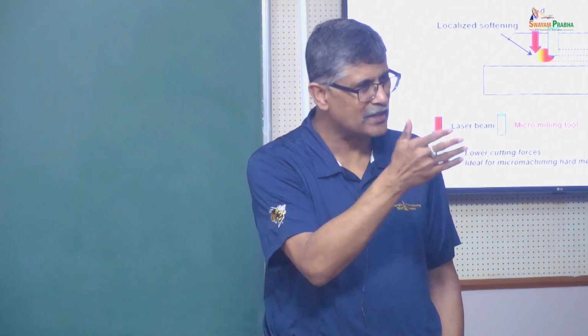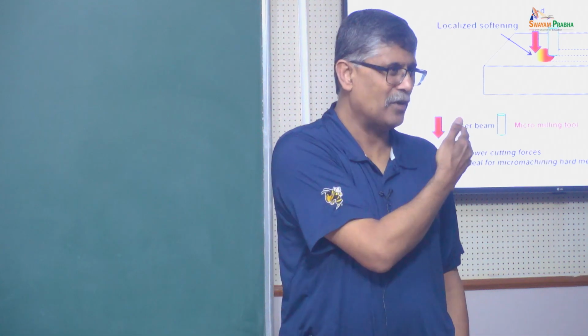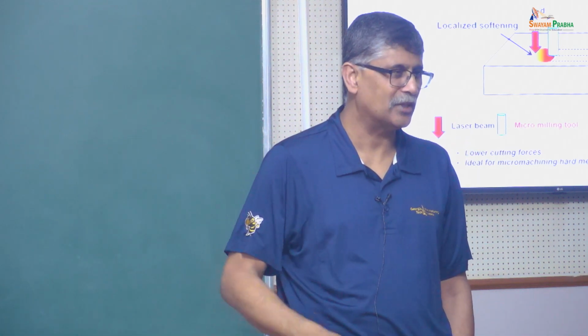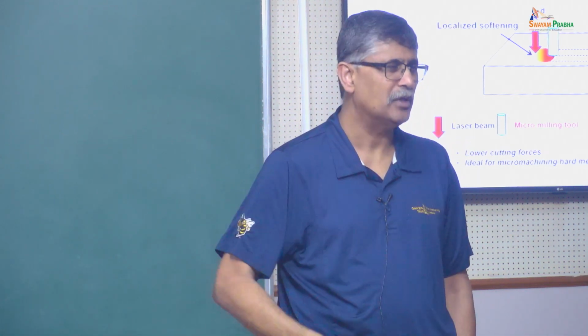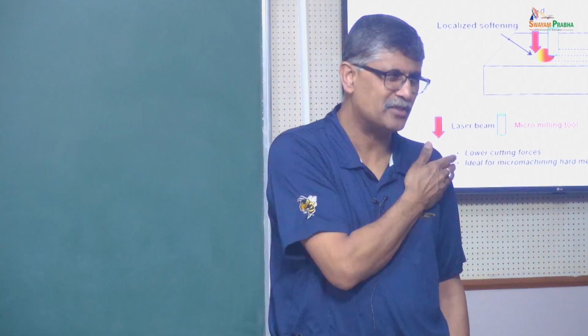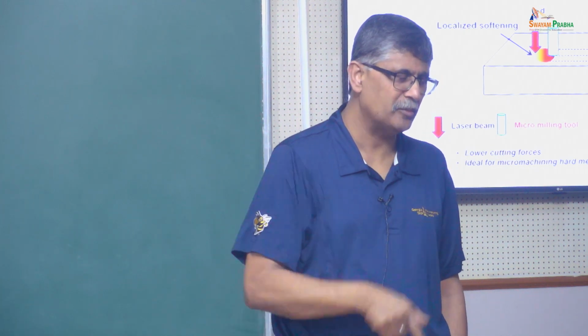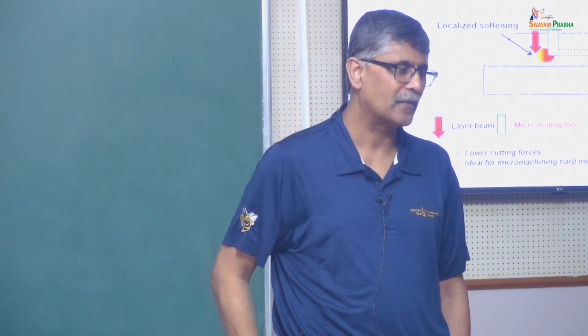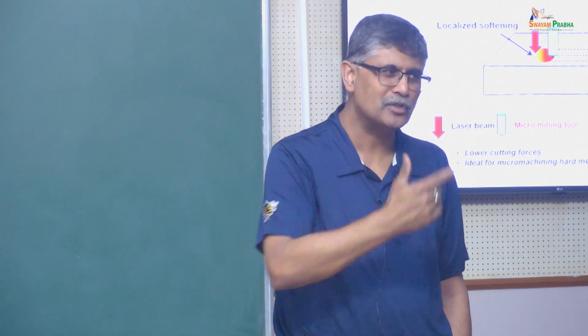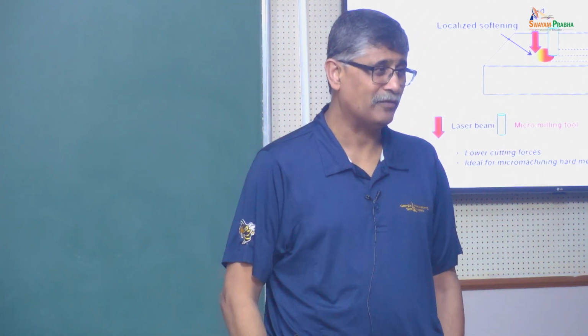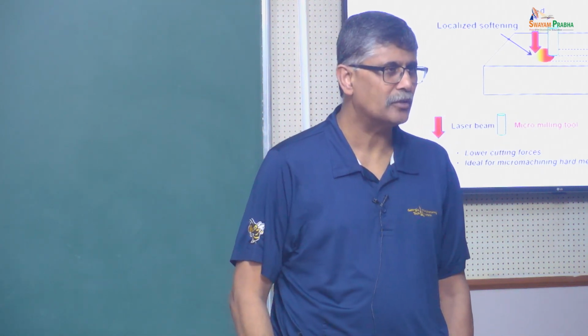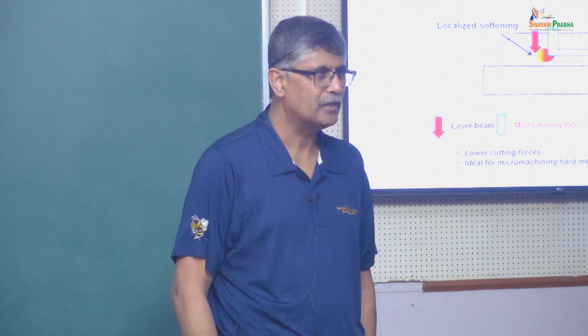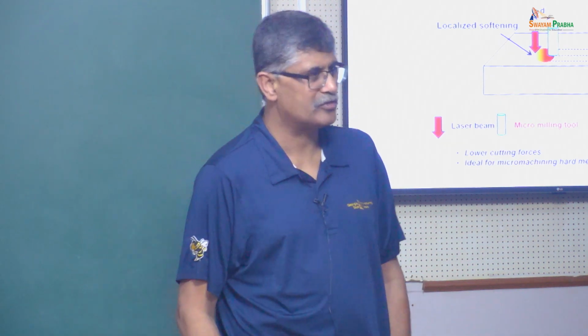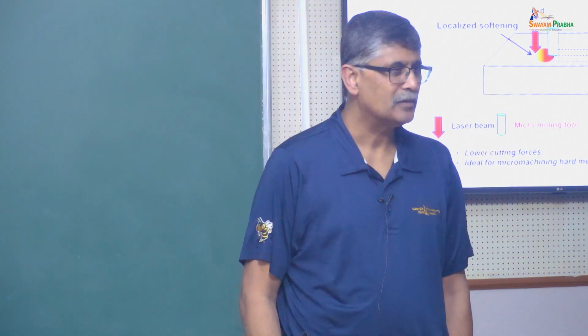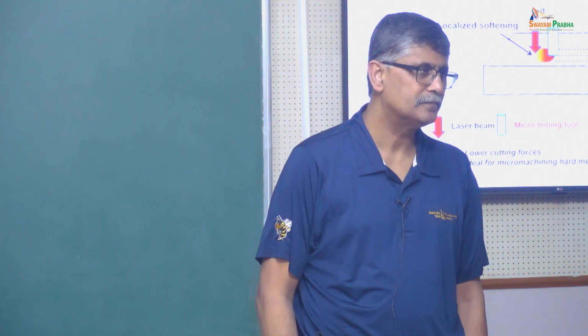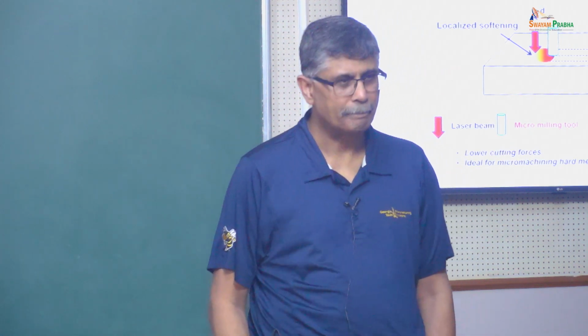Indeed, we have used that type of a model to build a model, but then you have to account for other effects too. The strength of the material is affected by the strain rate as well, because you're deforming the material at much higher, faster rates here. The micro milling tool is spinning at high speed, quite fast, right? So yes, you can use that type of approach, but it's the material property that is being changed that you have to account for, because you're thermally softening it. Thank you, sir.